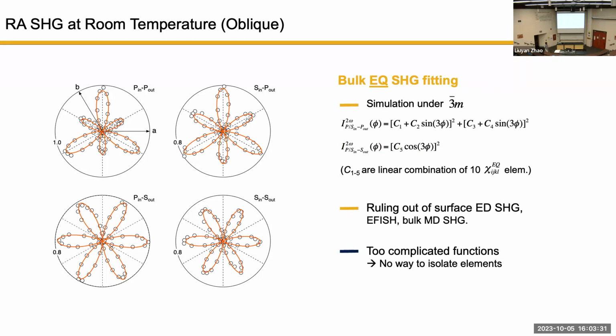And by doing so, we can also rule out other possibilities. For example, you may ask, the surface breaks inversion, how do you know your data is not coming from surface electrodipole SHG? The reason is that it will show a different flower pattern after we simulate it out. And our data is distinctly different from that. And then it rules out electric-field-induced second harmonic generation and bulk magnetic dipole SHG. So that leaves us confidently with this electroquadrupole SHG.